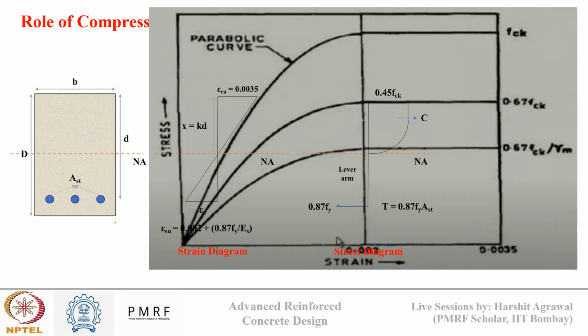Now concrete in structural design does not reach full cube strength in practice, especially when we are talking about cylindrical samples. Therefore we need a conversion factor of 0.67 to account for the difference between the cube strength and the cylindrical strength. So this initial conversion factor is for the shape of concrete. Now the second factor, gamma m, is the partial factor of safety of material, which is typically 1.5 for concrete as per IS 456.